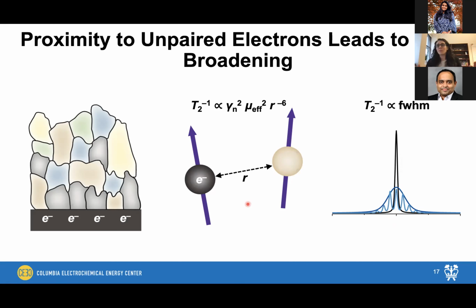So sometimes this broadening effect can be so bad that our NMR signal is actually completely broadened into the baseline and you get no signal at all. So that's basically worst case scenario. So we want to stay away from stuff that's very, very paramagnetic because we're actually not going to get any signal from those types of materials.